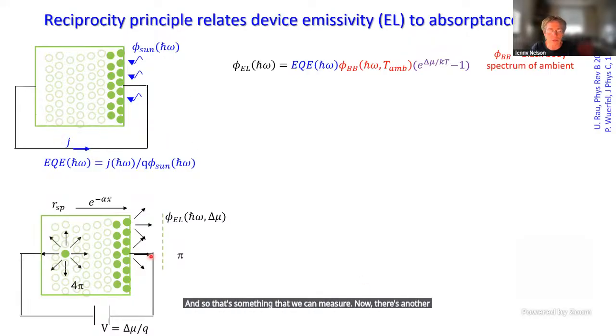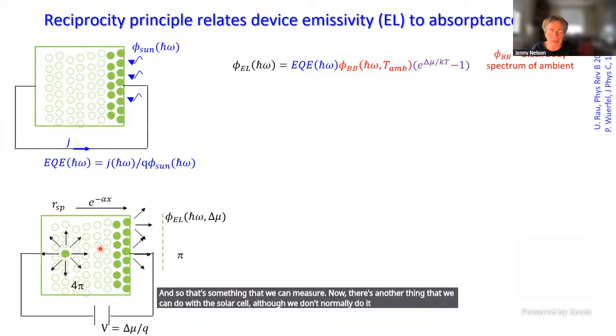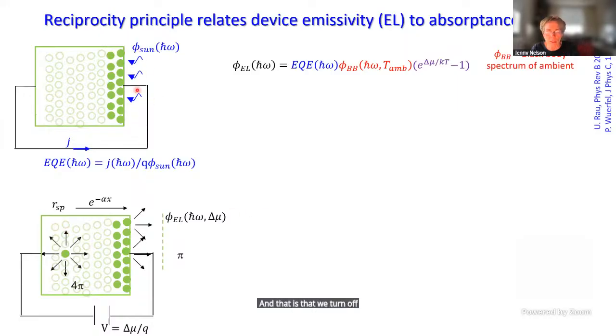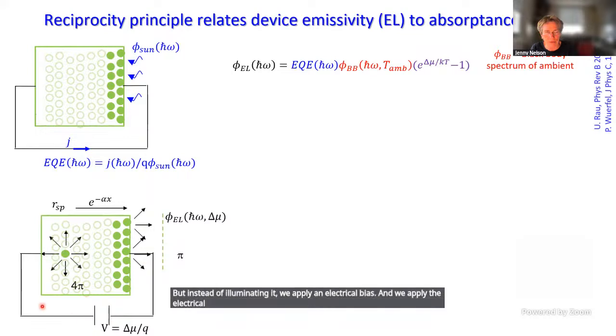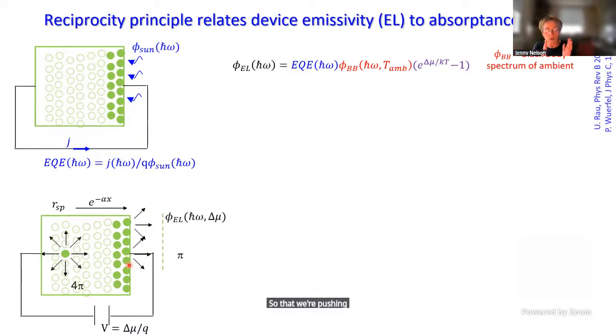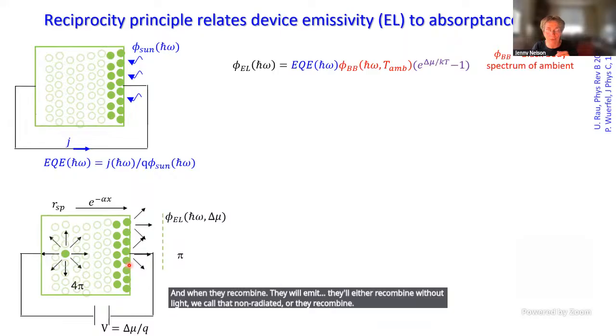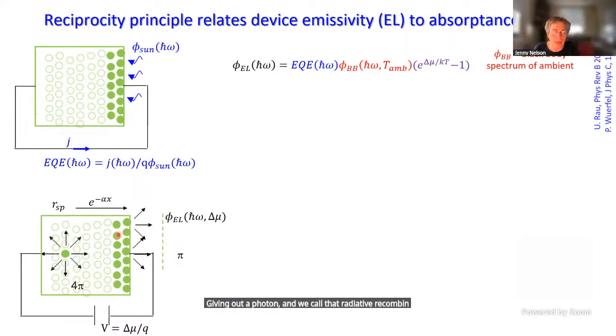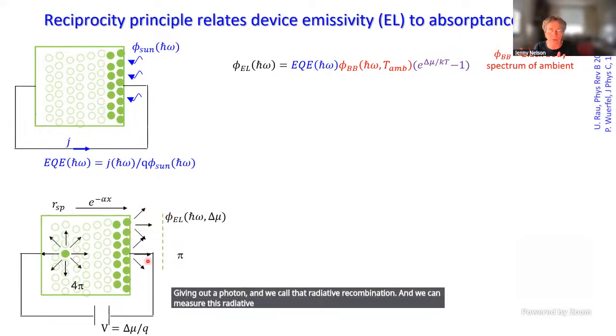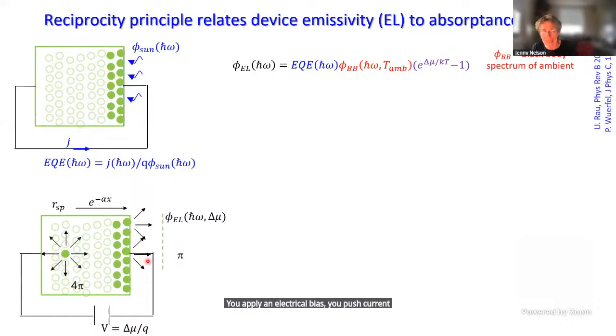Now, there's another thing that we can do with the solar cell, although we don't normally do it. We don't illuminate it; instead, we apply an electrical bias to drive the current the other way, so that we're pushing electrons and holes into the semiconductor from the contacts. And then when they come in, they recombine. They'll either recombine without light, which we call non-radiative, or they recombine giving out a photon, which we call radiative recombination. We can measure this radiative recombination that comes out of the device, which we recognize as electroluminescence. That's the same as the idea of using a light-emitting diode: you apply an electrical bias, you push current in, and you get light out.